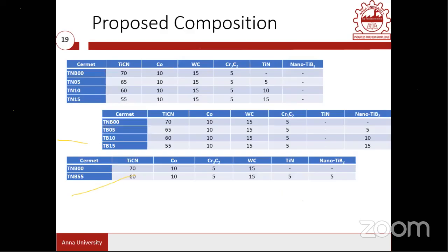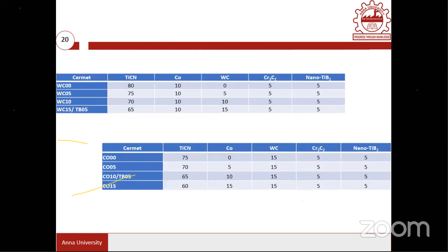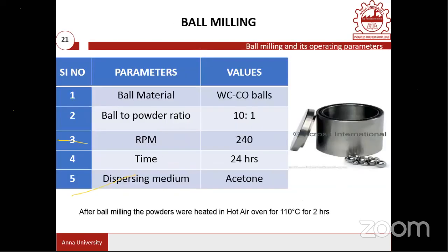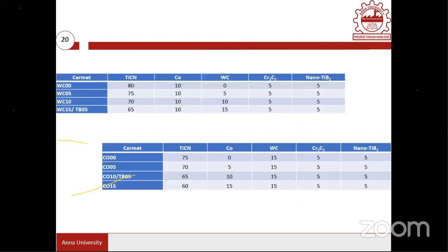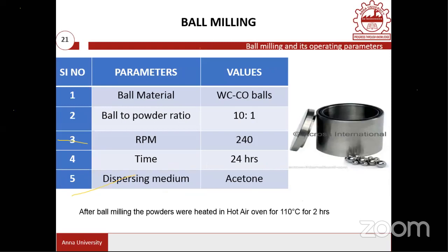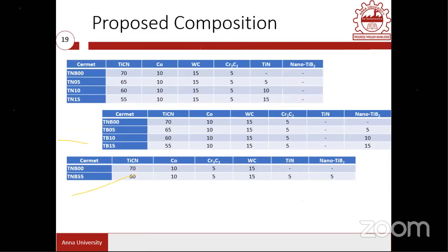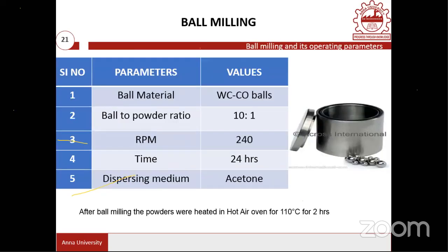And now I proposed a table in which we have several compositions, and initially the powders will be taken in the required quantity and ball milled. So that means the number of experiments that we have conducted is really huge. For each case, we have prepared the powder composition separately and sintered the material. Then the experiments include the measurement of mechanical properties as well as thermal stability, mechanical wear resistance, everything.